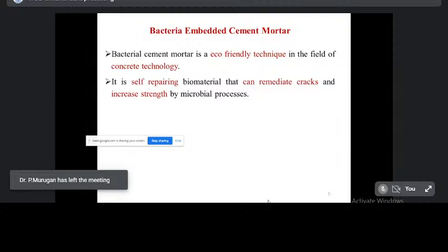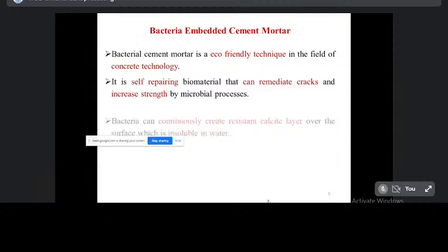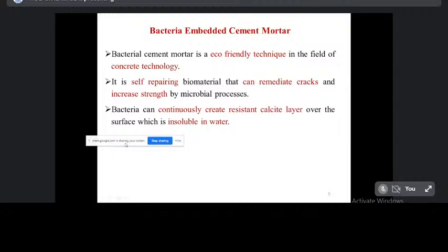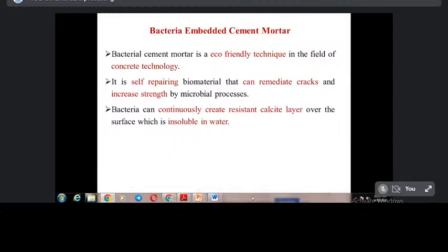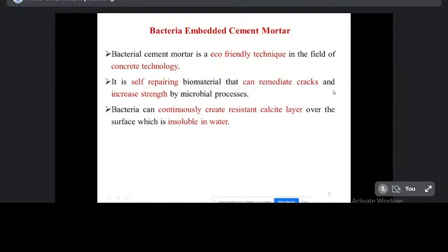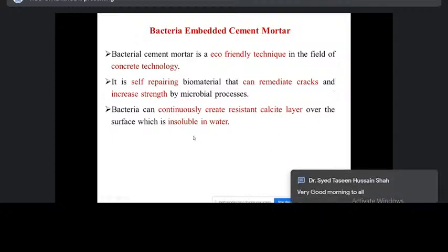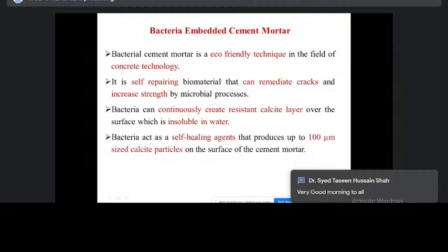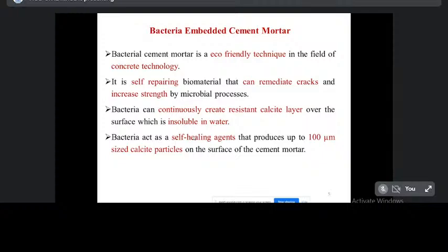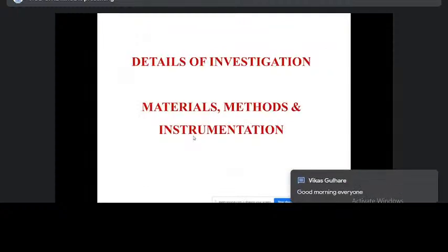The bacteria produce some calcium carbonate. That calcium carbonate fills the voids between the cement and sand matrix. So automatically the strength and durability characteristics of the cement mortar will increase. Bacteria can continuously create a resistant calcite layer over the surface which is insoluble in water. Bacteria act as a self-healing agent that produces up to 100 micrometer sized calcite particles on the surface of the cement mortar. It is an important area of research for high performance construction material.